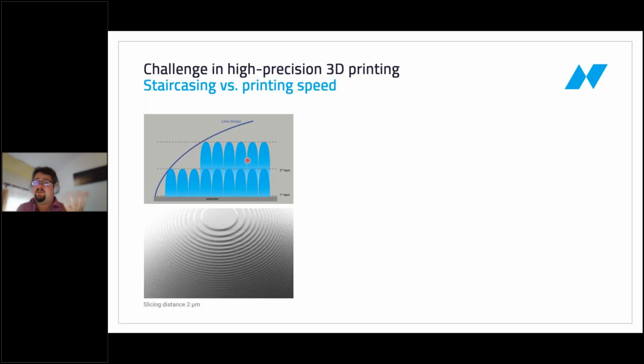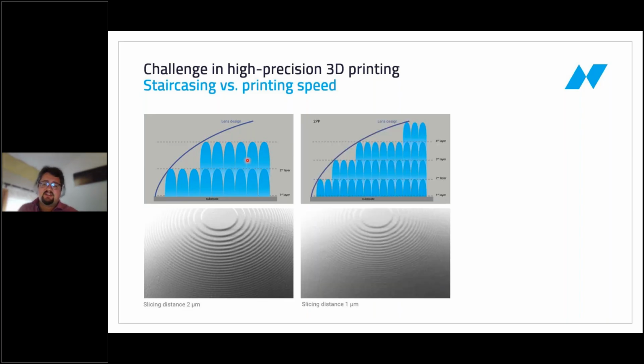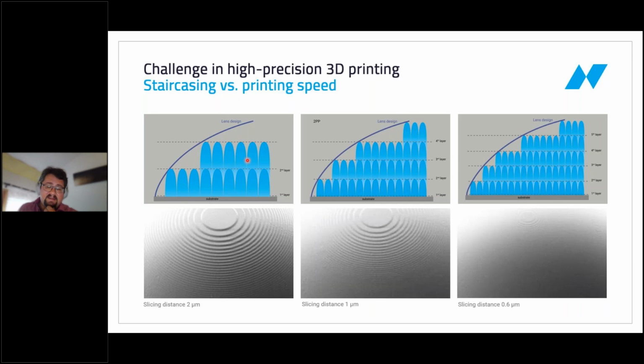This works well, and you somehow have to discretize it if you want to build it layer by layer. But for some examples, specifically the optics that we have mentioned several times, this gives you the challenge of having a surface quality that is not really suitable for optics. There could also be other medical, biological, or fluid dynamic applications where those surface roughness introductions could not be ideal. You can overcome this by reducing the slice thickness, making it thinner and thinner, and at some point the steps basically wash out and you end up with a very smooth surface.